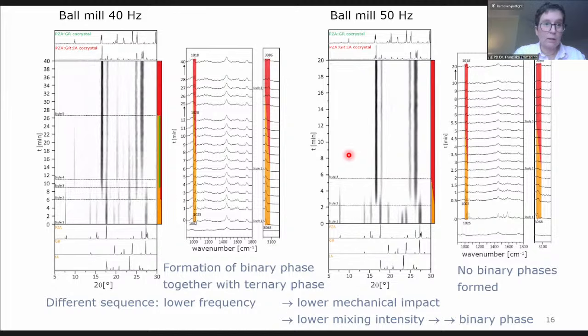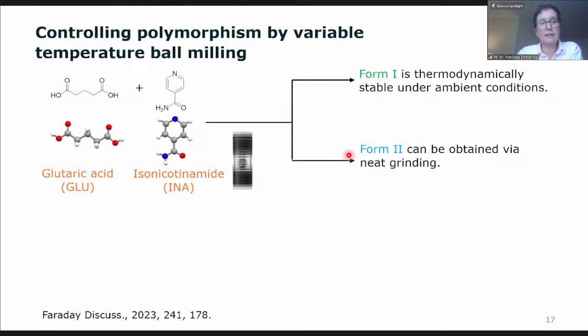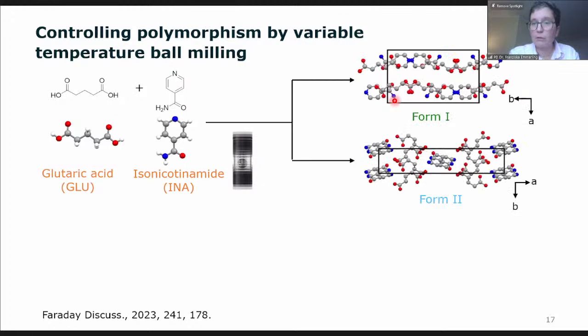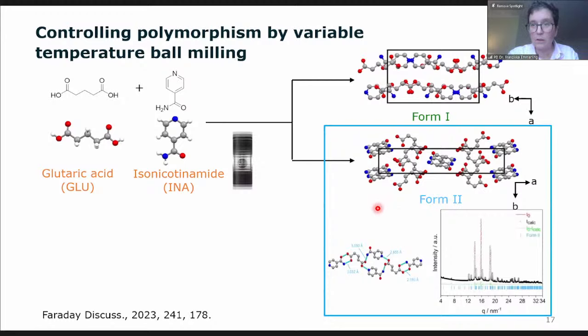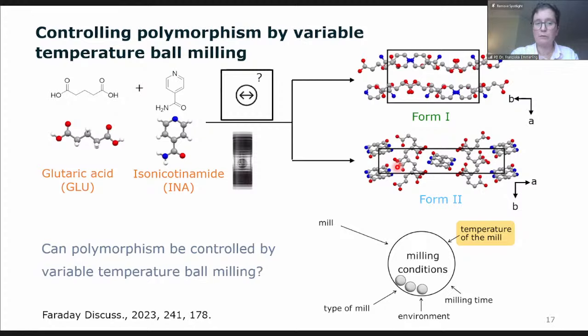Okay, another co-crystal example I will show on the next slides. And here we were a bit more interested in the effects that temperature could have on the milling process. You can see we skipped pyrazinamide, so it's only glutaric acid and isonicotinamide in that case. We knew the existence of form one, but you know these co-crystals, they like to form polymorphs. So there is a second form that you can only obtain under neat grinding conditions. And as I said, if you come up with a new structure, you need to solve it from powder diffraction data. And that was possible here. You see the Rietveld refinement, and then we could assign this structure. So we were interested now whether we can control the polymorphism by controlling the temperature in the ball mill.